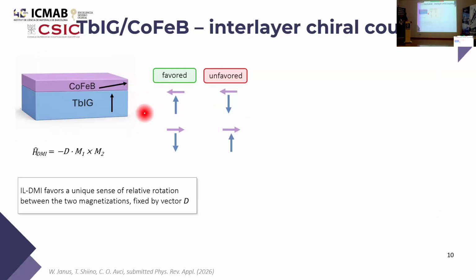So this actually motivated us to explore more the possibilities behind the couplings between the garnet and the ferromagnet. In the next research, we focused on a simple bilayer system, where we have terbium iron garnet with perpendicular magnetic anisotropy and a ferromagnetic layer, this time cobalt iron boron, with uniaxial in-plane anisotropy. For this new system, in addition to the collinear coupling that we also explored for the previous system, we also found some chiral coupling between the two layers. This chiral coupling is related to the interlayer Dzyaloshinskii-Moriya interaction. For now, the most important thing about this coupling is that it favors a unique sense of relative rotation between the two magnetizations. This simply means that with this chiral coupling, we can have different states in our samples, favored and unfavored, meaning that there is some preferential relative orientation of the magnetizations between the two layers.